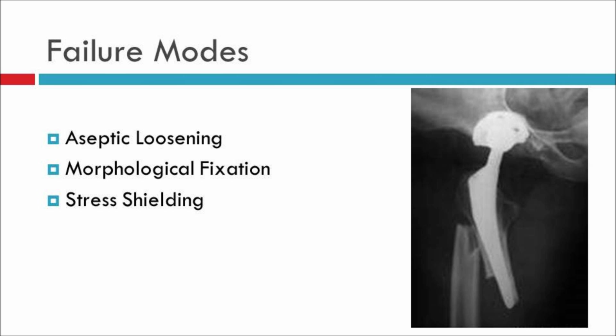The third, which is of particular interest, is stress shielding. This occurs because the modulus of the implant material is generally much greater than that of bone. The implant material takes the brunt of the mechanical load during walking. One important thing is that bone is a dynamic system and requires mechanical stimulus to stay strong. When not appropriately stimulated, it begins to atrophy and weaken. You can see the picture to the right shows what a typical failure would look like due to weakened bone. You can see fracture at the femur and hip stem interface.